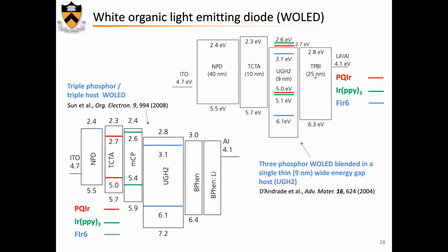One is where you put the three phosphors, the red and the green and the blue, in a single large band gap host, and electrons and holes, of course, find their ways to these different molecules and so on. And so here you would have the blue and the green and the red, and these are the molecules involved. And another configuration, of course, is the triple phosphor, triple host, where the blue is in one material and the green another and the red in another. And of course, the technology and the design is quite complicated. You have to have exactly the right thickness and the right density of these phosphor molecules in there, but they are getting very, very good at that.